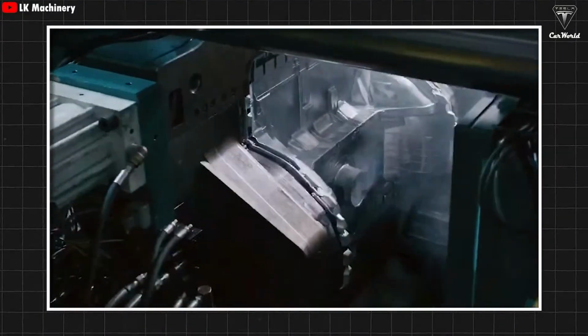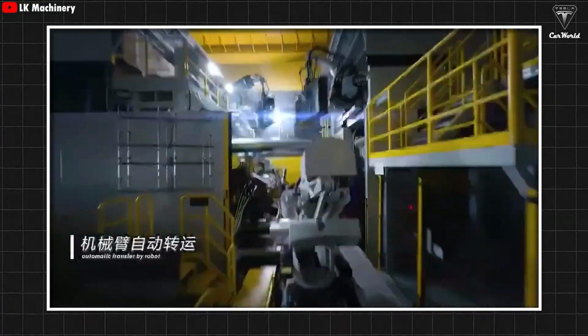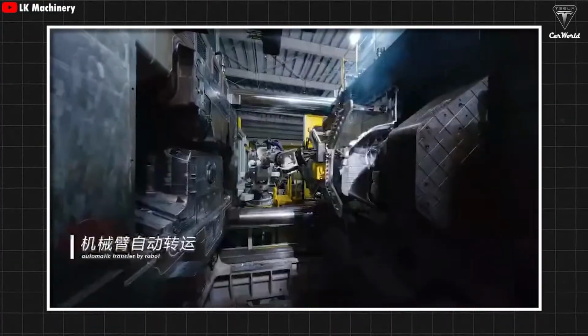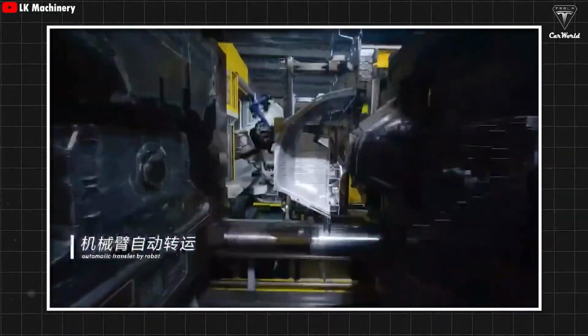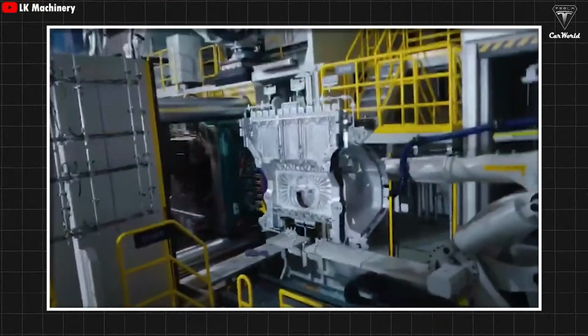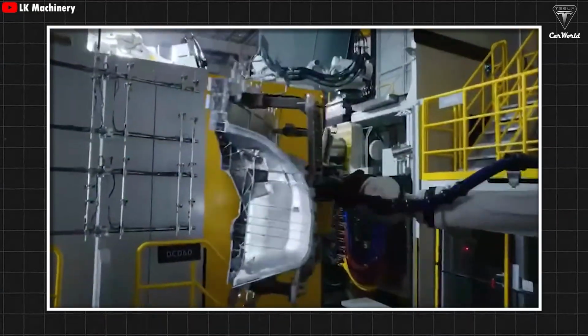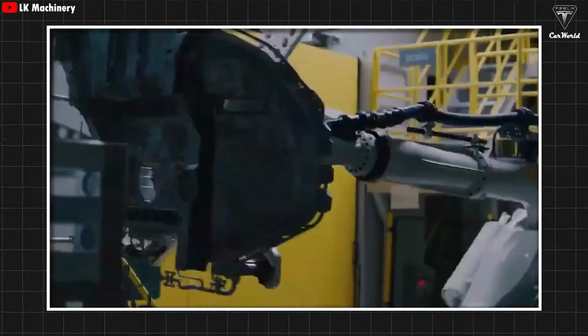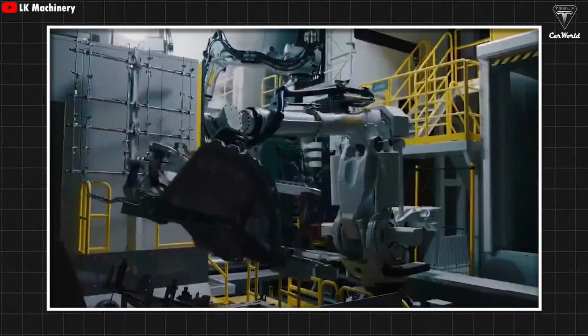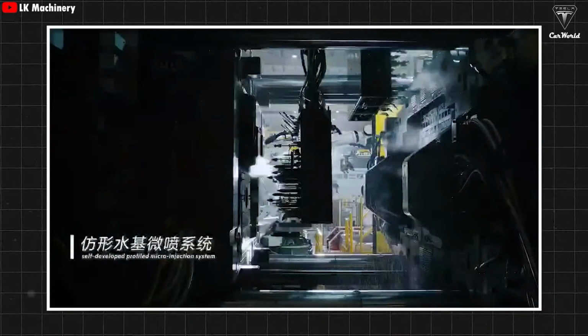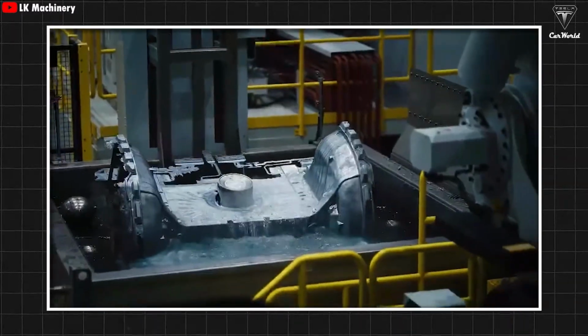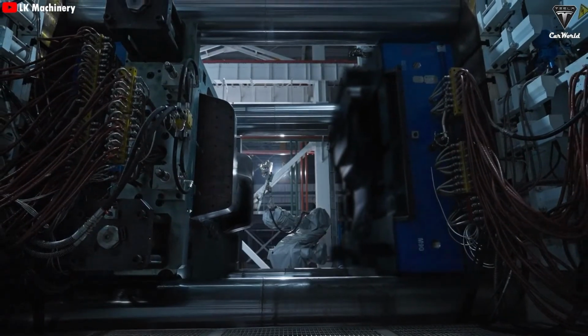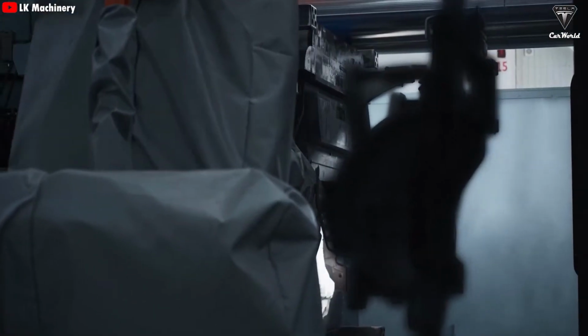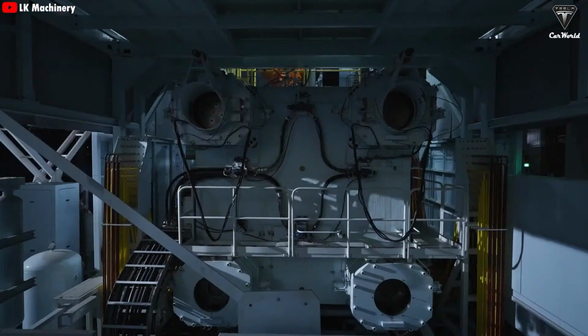The Giga Press applies ultra-high pressure to ensure the molten aluminum fills every tiny detail of the mold perfectly, leaving no defects. Once cast, the part is evenly cooled, causing the aluminum alloy to harden into its final shape. This process requires extreme precision. If it's too fast, air bubbles can form. Too slow, and the aluminum starts cooling before fully filling the mold. The cooling process is carefully controlled through a uniform cooling system, which helps the final product achieve high strength and